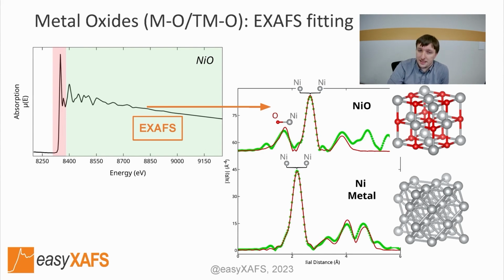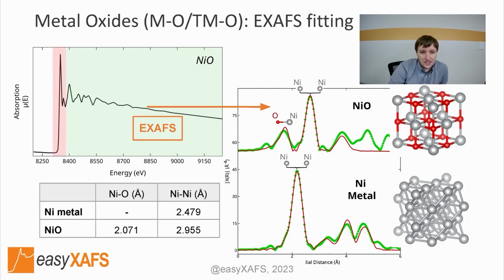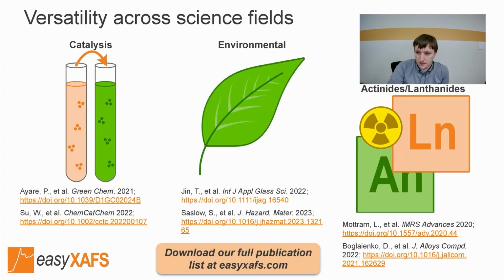These XAFS oscillations can be described in terms of atomic distances, as shown here for the nickel oxide and nickel metal systems. In this case, the nickel oxide has 2 distinct features between 1 to 3 angstroms associated with the nickel-oxygen and nickel-nickel atomic distances in the rock salt structure. The nickel metal has a single nickel-nickel peak. XAFS fits of these structures provide direct insight into the atomic distances, which can be valuable in identifying material or observing the evolution of a material structure.